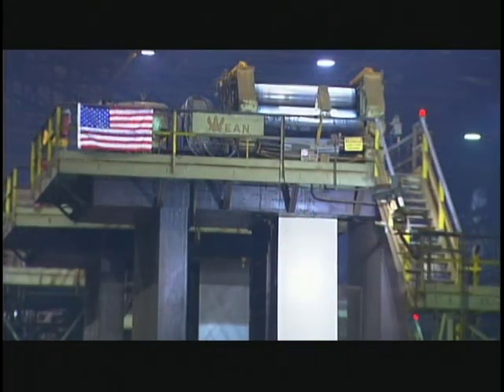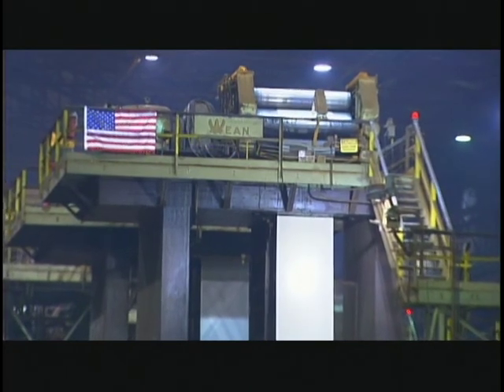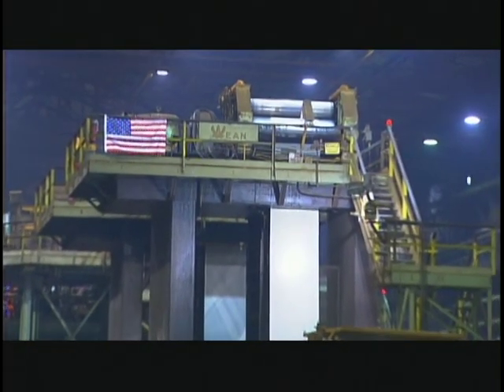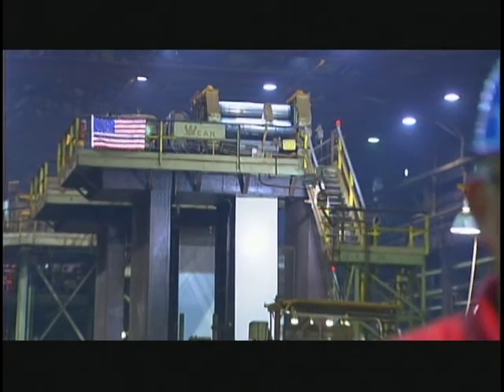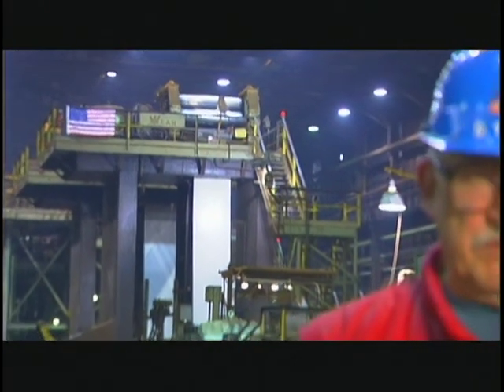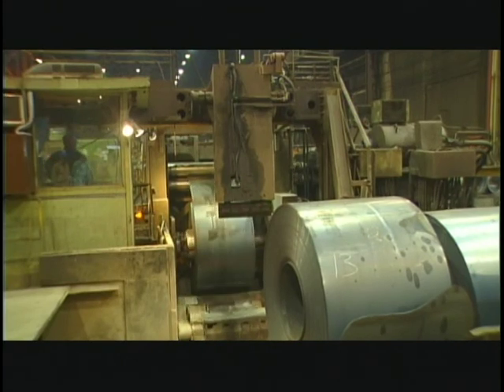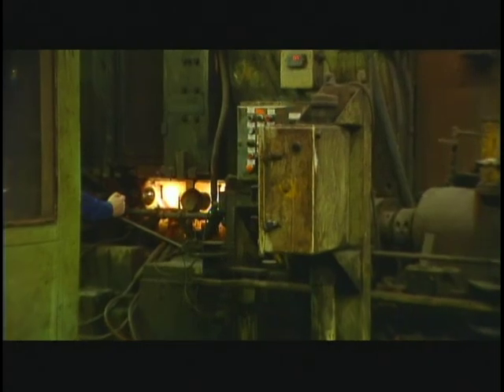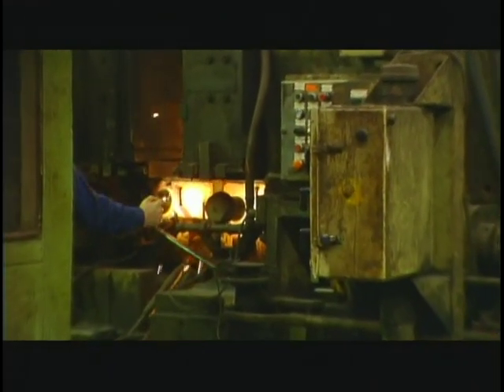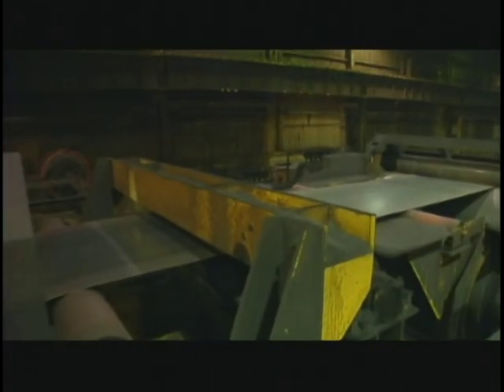Here at the start of the finishing mill, we have 2 80-inch continuous picklers. We're running 2 types of products, being cold roll and hot roll pickle. Starting at the process at the beginning of the pickle line, we'll crop the head and tail ends in preparation for welding them together to remove the scale and make the strip flat using an 80-inch bliss mill and an acid hydrochloric bath maintained at 6.5% to 7.5% and at 190 degrees to 195 degrees temperature.